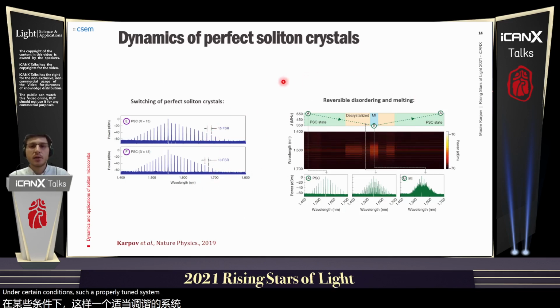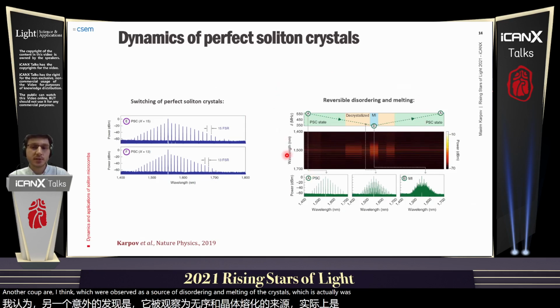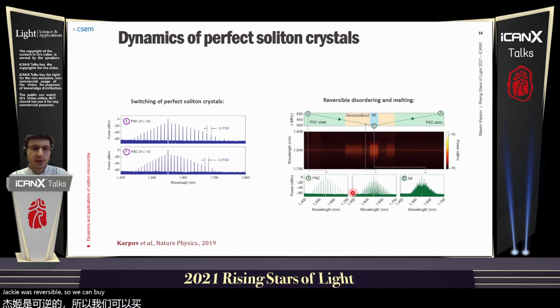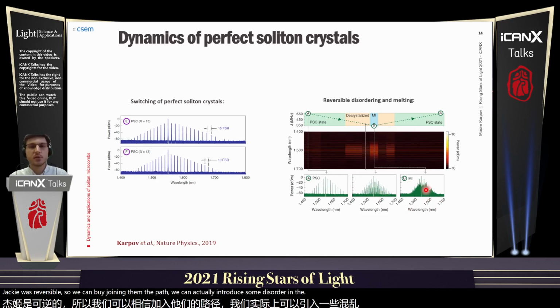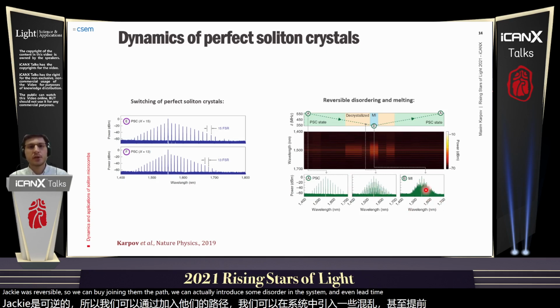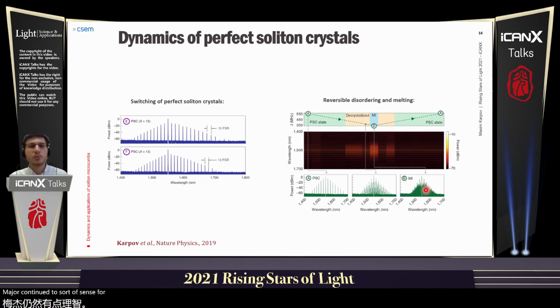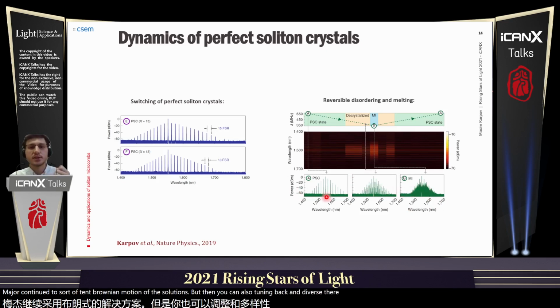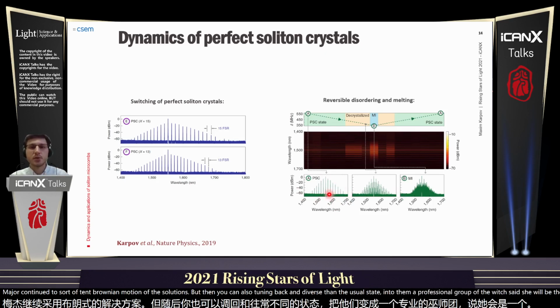Another cool thing which we observed is the so-called disordering and melting of the crystals, which was actually reversible. By tuning the pump, we can introduce some disorder into the system and even lead the intracavity field to Brownian-like motion of the solitons. But then you can also tune it back and reverse the initial state into the perfect soliton crystal state, which would essentially be the same as you had before. So you can melt and recrystallize the soliton crystal state.